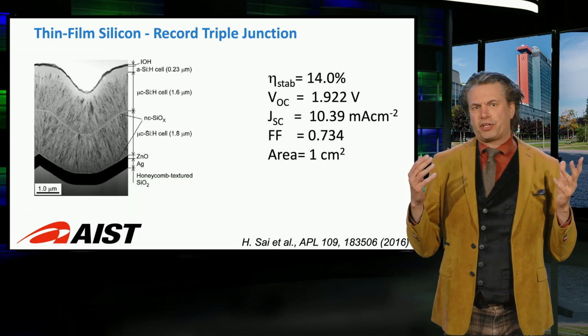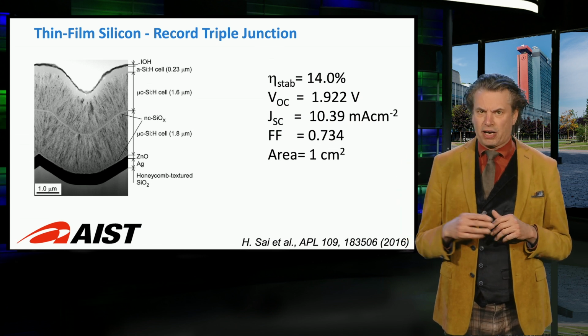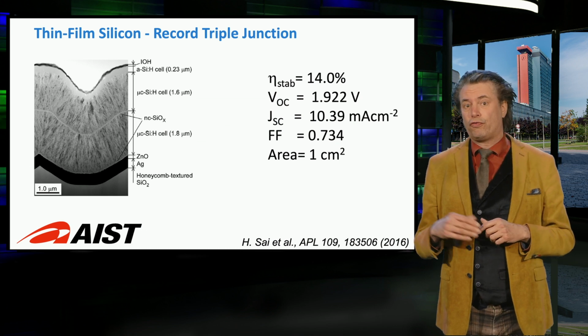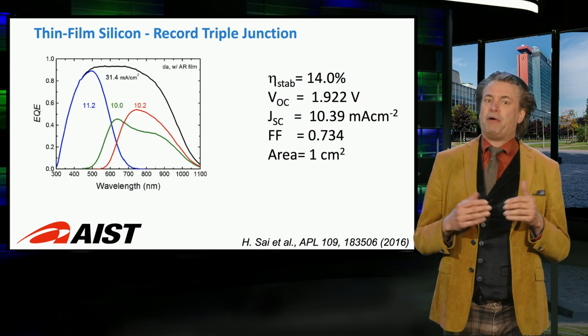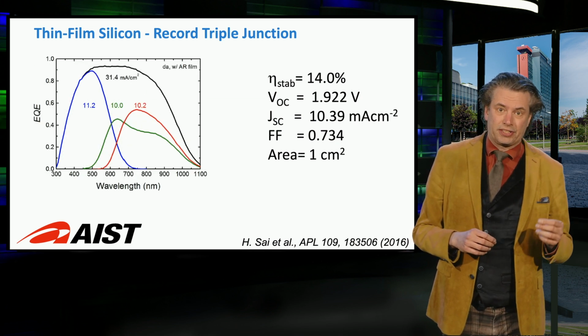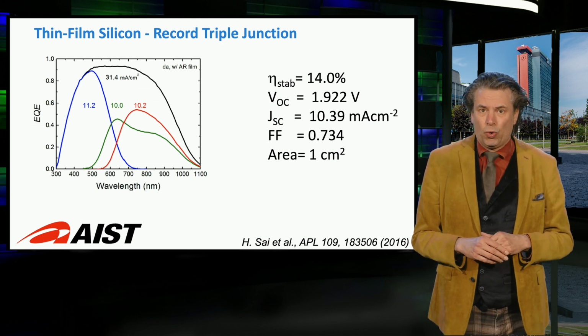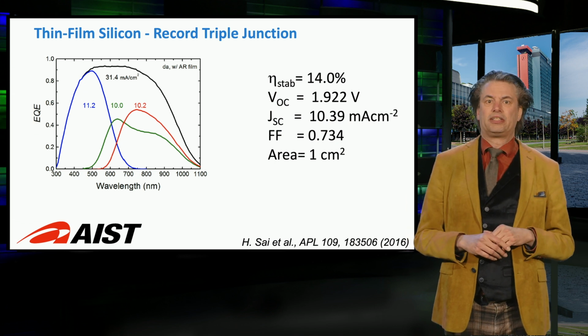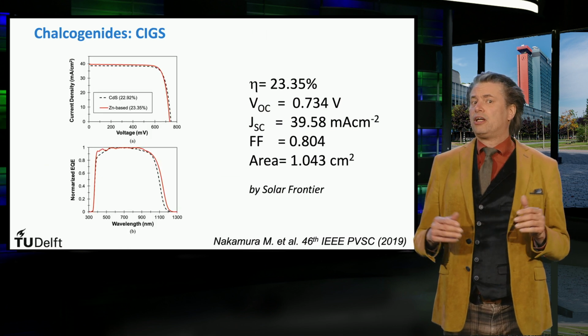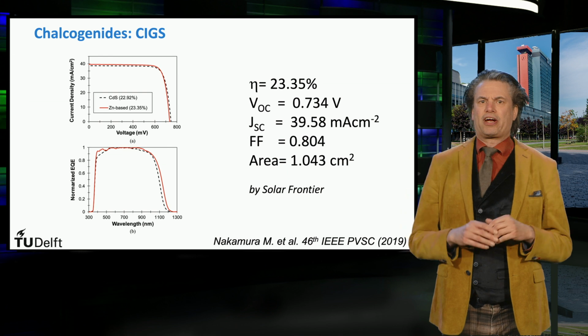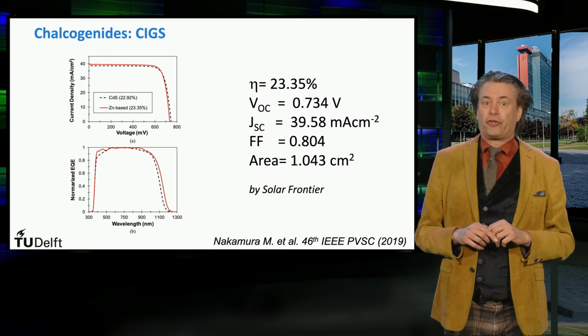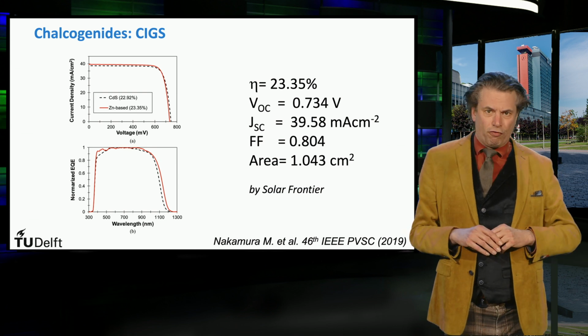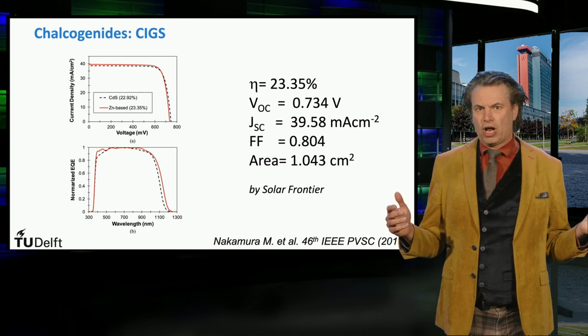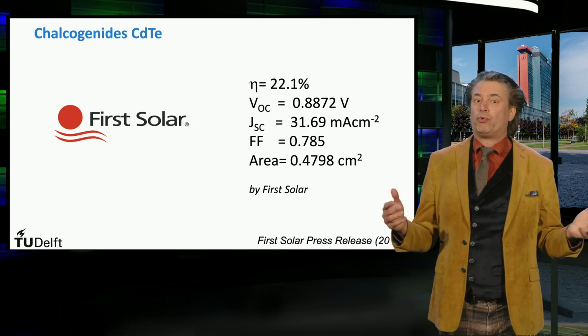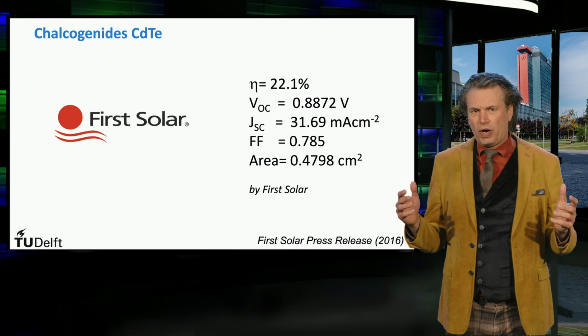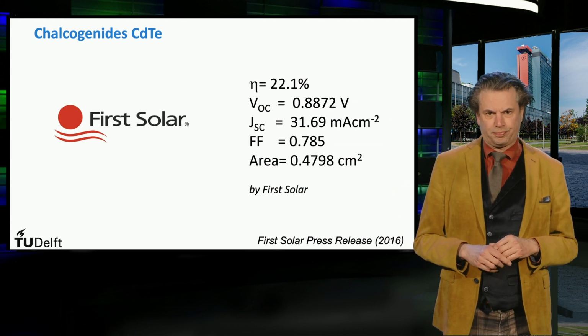If you focus on the most important thin film PV technologies, we see that the record stabilized efficiency for thin film silicon PV equals 14%. This PV cell is based on an amorphous nanocrystalline triple junction processed at AIST in Japan with a lab cell device area of 1 square centimeter. Solar Frontier, the leading CIGS module manufacturer, has set the world record for the CIGS PV devices to 23.35% with a lab cell having an area of around 1 square centimeter. First Solar, the leading cadmium telluride manufacturer, is responsible for the world record for thin film cadmium telluride PV technology, which equals 22.1%.